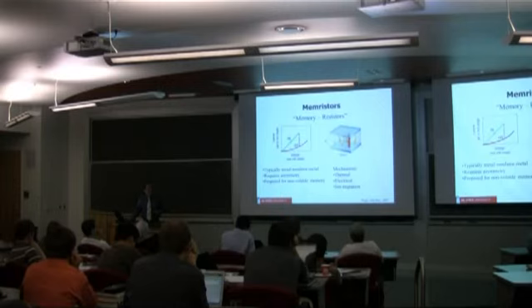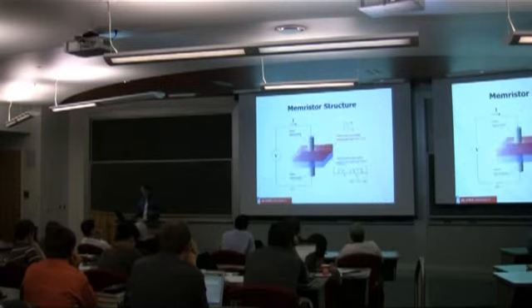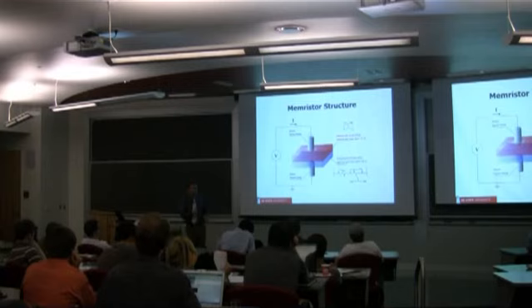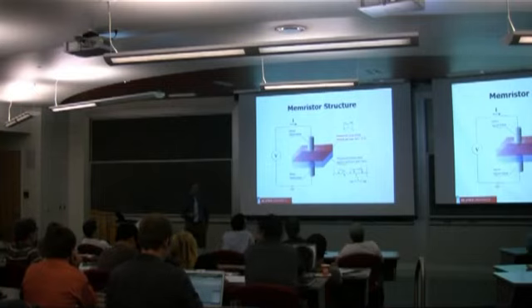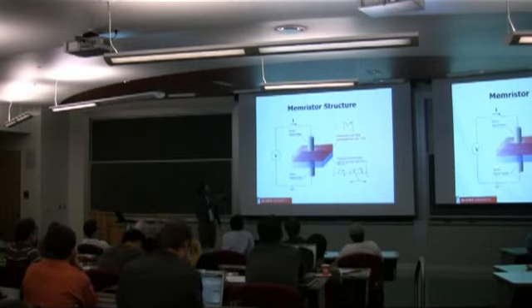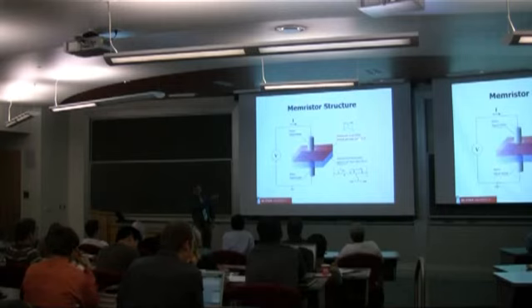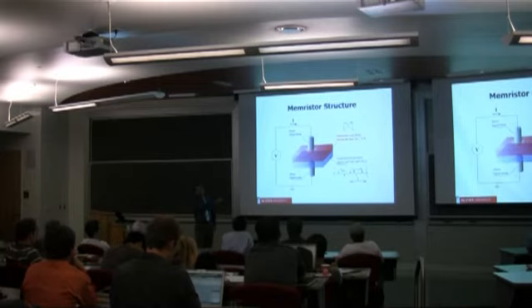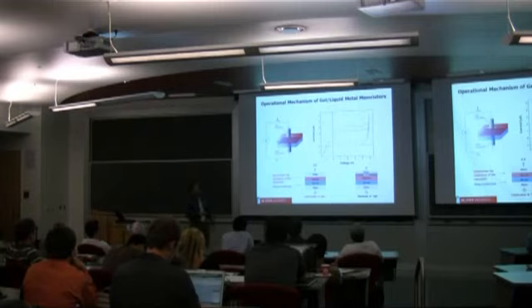Now, we've been able to do this using Jello, so to tell you exactly how this works. For a memristor, you have to have asymmetry. What I mean by that is the top of the device has to look different than the bottom. And in our Jello-like device, we do that by doping these hydrogels with polyelectrolytes. That's just a fancy word for ionic polymers. And we dope this red-colored layer with an acid-like polymer. So it has a very low pH, it's acidic. This layer, we dope it so that it is basic. So we now have asymmetry. The top layer, which has this metal contact, is now in contact with an acid, and the bottom part is in contact with the base. And that matters. And so I'll walk you through how this works.